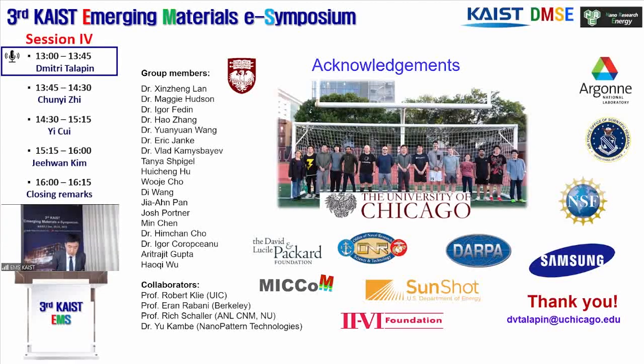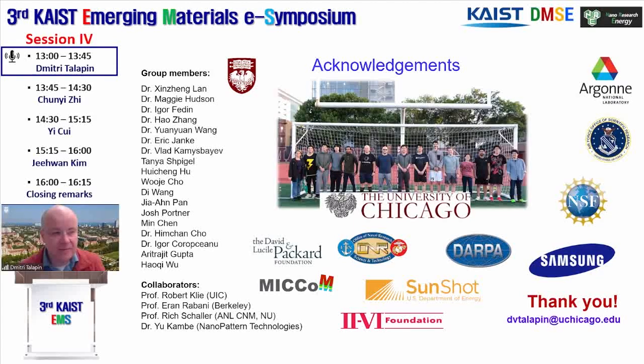Okay, thank you. The last question: which is a more important factor between reaction time and temperature for quantum dot synthesis? Do you think it is possible that the cation exchange with other ions can obtain high entropy alloy semiconductor quantum dots? Yes, I really believe at the moment that the sky is the limit. We can do a lot of complex compositions. We now have up to 5-element III-V phases, so we can mix pnictides. We can mix gallium, aluminum, indium in these structures. We didn't think about this from the point of view of high entropy alloy structures, but I think it's pretty close to high entropy alloy systems.